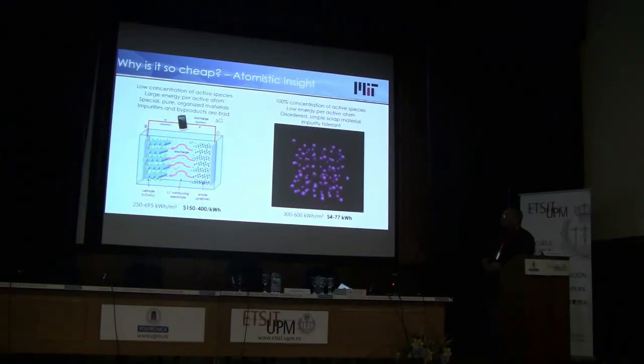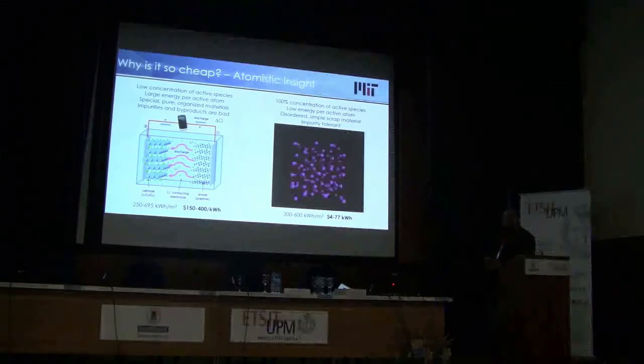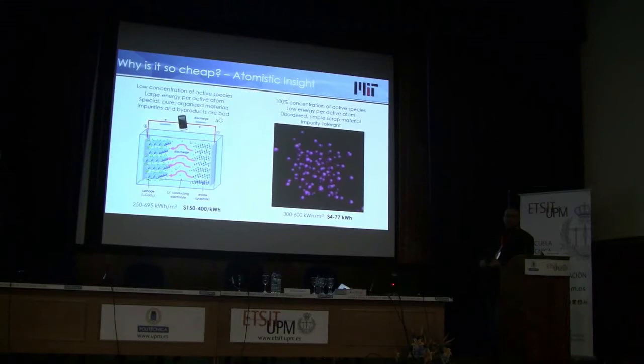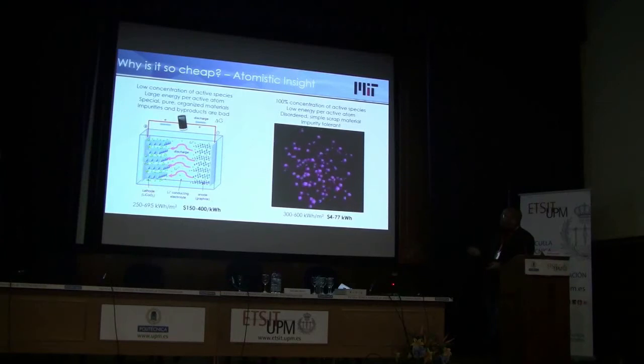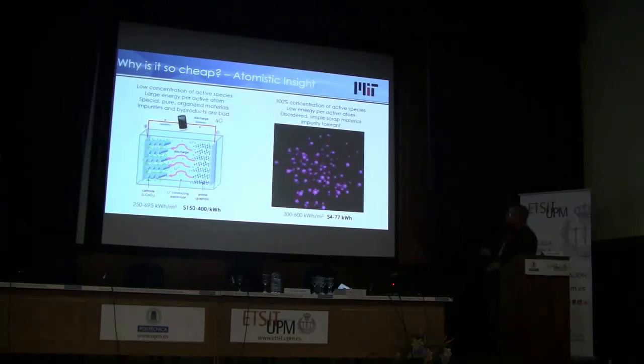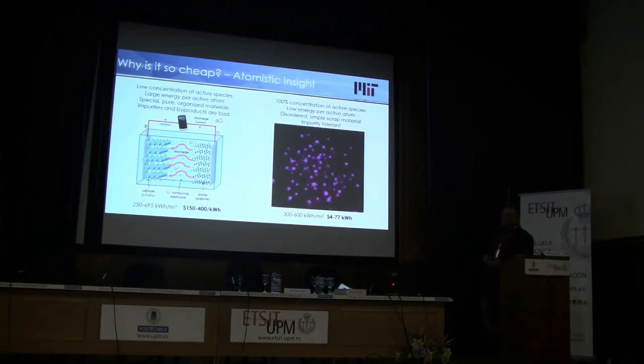Conversely, with heat, you're storing a very small amount of energy per atom, but you're storing it in effectively every atom in the system. And for this reason, it's very robust in the sense that we don't really care where the atoms are or how they're moving. We have long lifetime in the sense that the only thing we're truly doing is heating up or changing the kinetic energy of the atoms, raising it, and then lowering it back and forth. In this case, I'm talking about sensible heat rather than phase change.